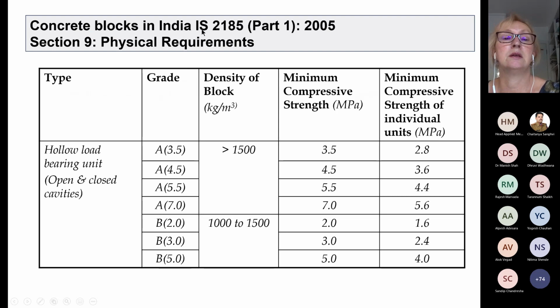In India, the standard where you can look for the specification of blocks is IS 2185 Part 1, which gives physical requirements for the blocks. We have different types of blocks. For load-bearing units, it is grade A block and grade B block. You can see the A or B, and in the brackets the number. The number is the compressive strength. The typical compressive strengths for the blocks are 3.5 megapascals, 4.5 up to 7 megapascals. And for B, it is smaller, 2, 3, or 5. I believe that you can specify differently if you order from the plant, but these are listed in the standards as typical strength. So maximum strength would be 7 megapascals.